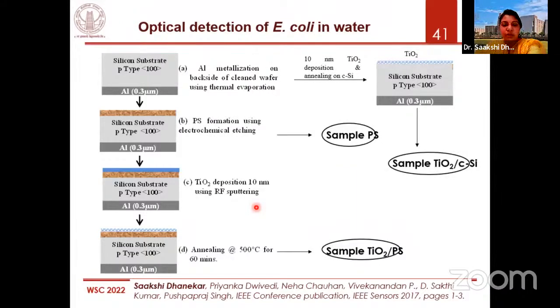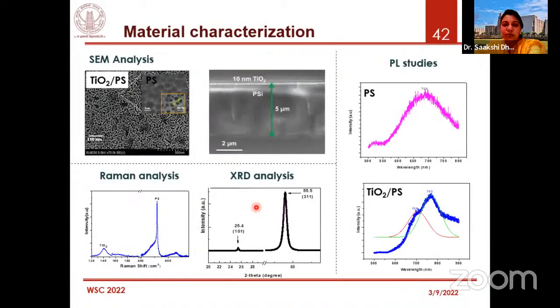So there, I had gone there for a few months, and then we could do some of the testing of our chips with bacteria being in water. So what we did here was that we used, again, our nanostructured silicon with 10 nanometer thickness of TiO2. But instead of doing these electrical measurements, we were more interested in the photoluminescence studies. This titanium dioxide has a very good PL response, and same as nanostructured silicon. So we wanted to see if this photoluminescence can get affected in the presence of bacteria, right?